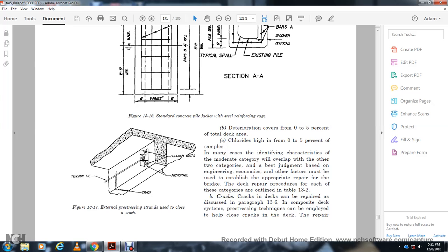Deterioration covers 0 to 5% of the total deck, and chloride is high in 0 to 5% of the samples. The main thing is to identify the character of the moderate category, which has an overlap with the other two categories. The best judgment must be made within engineering, academic, and other factors that must be established. The appropriate repair for the bridge deck is the repair procedure for each of the categories outlined. Figure 13.2 shows the deck preparation. The scope in 13.16 is the composite deck system.